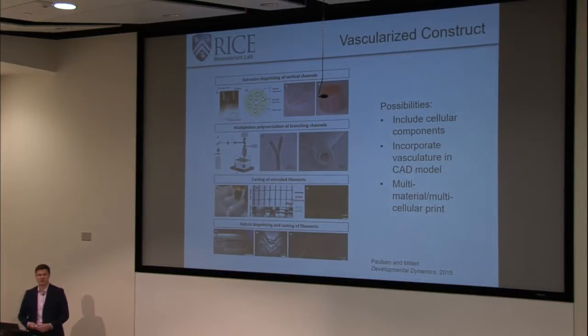And if we give that construct time, we do get full recovery of the cells because in this case, at least, the gelatin that we're printing with protects the cells a little bit from that thermal stress. So again, that goes back to always considering, while we're making these compromises with things like temperatures and the printability of our bioink, what we're really considering is how that scaffold will perform over time and what kind of post-processing techniques are necessary to make our bioink functional.